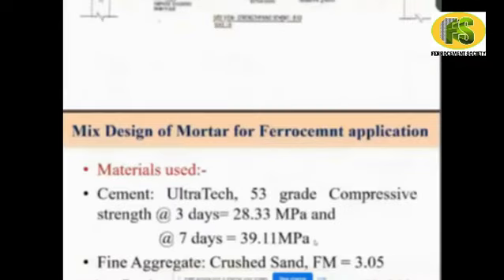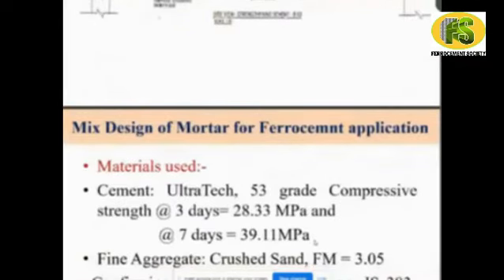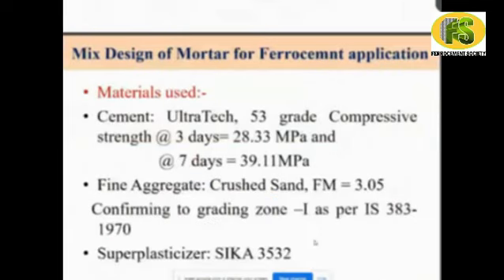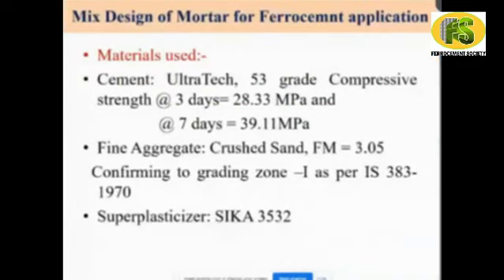One beam and one column were already done before, strengthened using ferrocement techniques. For the ferrocement, we designed the mortar in our laboratory with the help of Lele sir. We used UltraTech cement 53 grade, compressive strength at 3 days is 28.33 and at 7 days is 39.11. Fine aggregate is crushed sand, with fineness modulus 3.05, conforming to grading zone 1 as per IS 383 1970, and the super plasticizer used is Sika 3532 for the mortar.